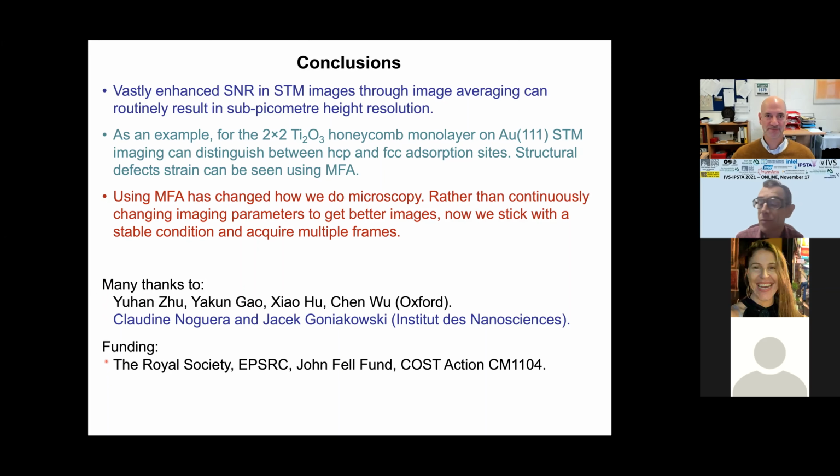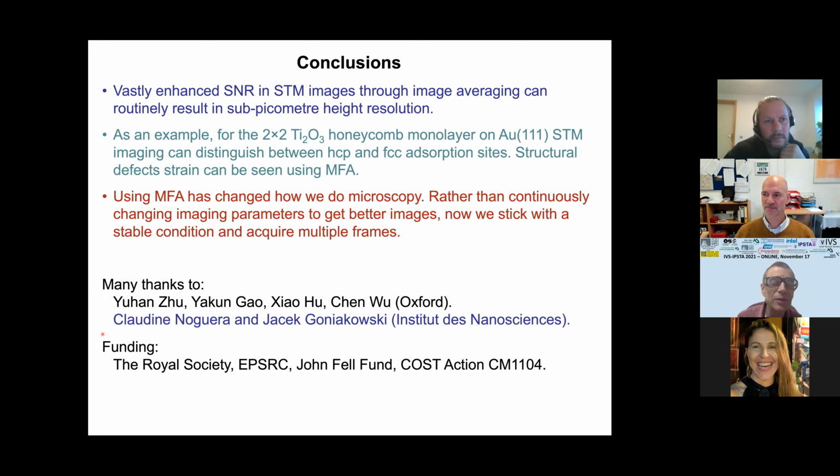Okay, great. Well, first of all, you leave us good time for questions. And second of all, it's really impressive. I mean, seeing a picometer resolution is something we can only dream of. But no, well, that's my point. You can't only dream of it, because we have a STM microscope. It's not a particularly fancy microscope, but what we do is just take, routinely, if you get a decent image, you take 65 of them. You don't just take the single image. So it's not something you can dream of. It's something you can actually do.